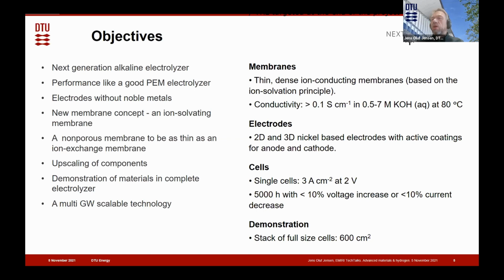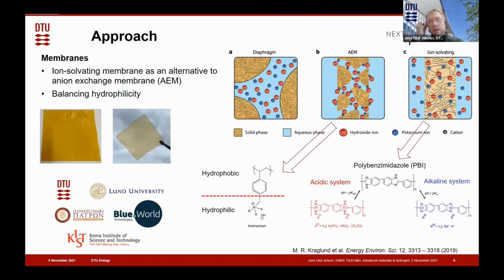And for the stack demonstration, we are aiming at full size, which is 600 square centimeter. This is something that fits a suitable stack design that NEL already has. And it is, of course, not as large as the large alkaline electrolyzers, but with the higher current density, it is perhaps not likely that the cells will be that large. But this is a practical solution that we will work with. But let me go a little closer to what it's really all about in the technique.